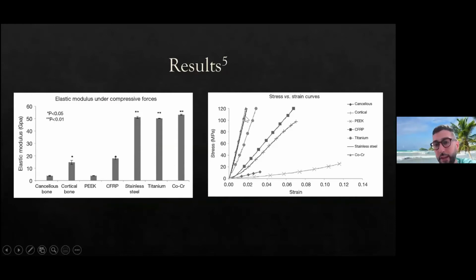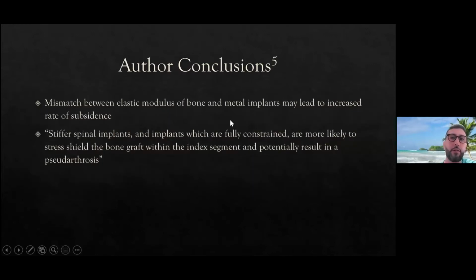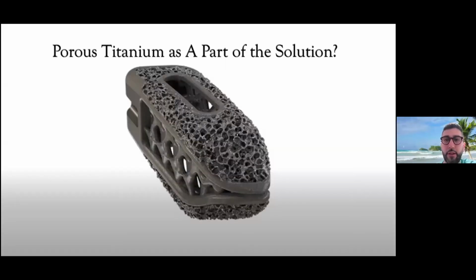And you see the same thing in the stress strain curves, which we now know is equivalent to this. That's how we calculate our modulus of elasticity. Again, if you go all the way over to the right, you see PEEK, and then you see the big difference between titanium, stainless steel, and normal cortical bone. And so what did they conclude from that study? They basically said that this mismatch between elastic modulus of bone and metal implants may lead to increased rate of subsidence. Obviously, they didn't specifically test that, but they did prove the difference.